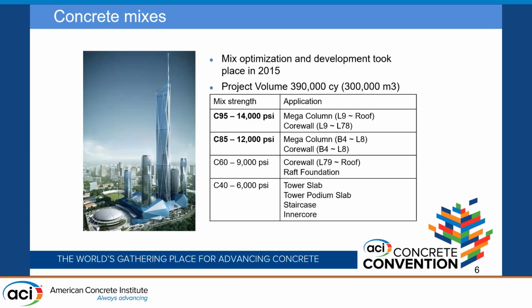Several different classes of mixes were required on this project, 14,000 PSI being the highest, and that covered basically from level 9 to the roof, and then level 9 to level 78 of the core walls. And we're going to talk about the mega columns and the mega core walls here shortly. And then the 12,000 PSI covered the basement level 4 to level 8 of the mega columns and the core walls. There were also 9,000 PSI designs, and one of these designs covered level 79 through the roof, core walls, and also the raft foundation.